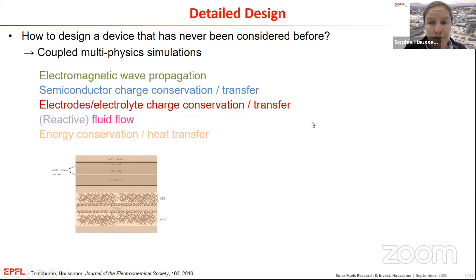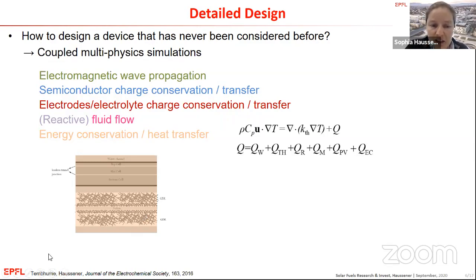Then the charge transport in the electrodes and the electrolyte, which in our case is a solid electrolyte. Finally, the fluid flow, reactive fluid flow in porous structures, and the energy equation as well. Somewhat new. The details of the implementation you can find in the reference indicated here. But you can see that the energy equation looks at first sight relatively simple. And then if you dive into the details, you see here basically a convection and conduction term, and you see a heat source term. And if you look into this heat source term, you see that you have a variety of contributions of heat sources coming from the different other physics.